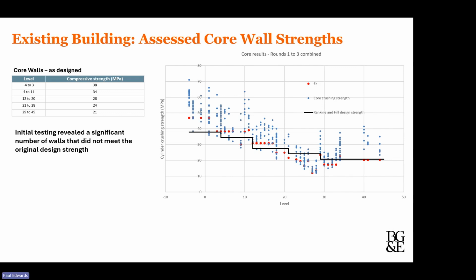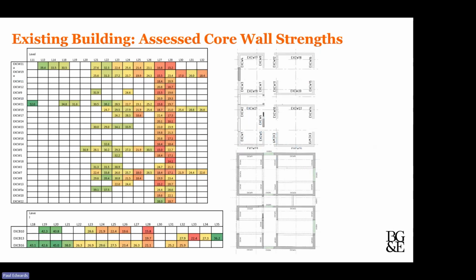So the investigation into the existing building revealed that actually the in situ strength of the material was below that identified as being necessary in the original design. And you can see in the chart everything below the black line, all those red dots below the black line, the F-C, resulting again from the ACI 214 approach, being areas where the concrete wasn't at the relevant level of strength. So the implications of that were relatively significant.